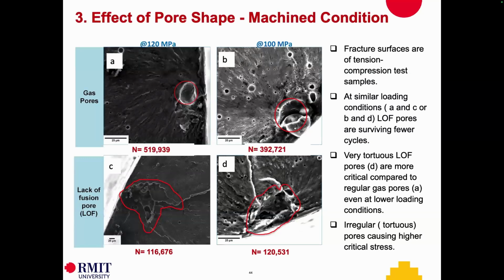Why is it? We know lack of fusion pores are notoriously tortuous, arbitrarily shaped, and have a lot of local stress concentrators embedded within the pore, which becomes highly fatigue critical and can initiate and propagate a crack at a much lower load. And it can significantly lower the fatigue resistance as we found here. So very tortuous lack of fusion pores are more critical compared to gas pores, and that is the key reason why we find at lower stress amplitude a high scatter with porosity, because of the shape of the individual critical pores which is causing the fatigue failure.